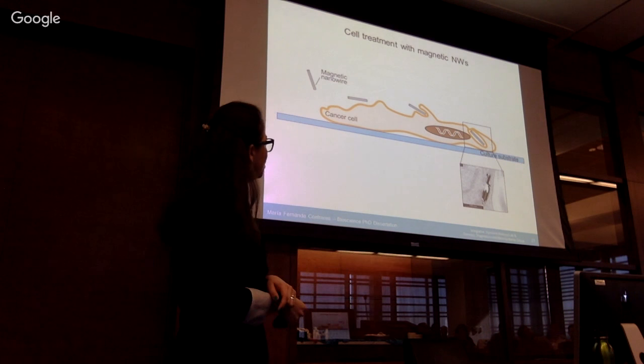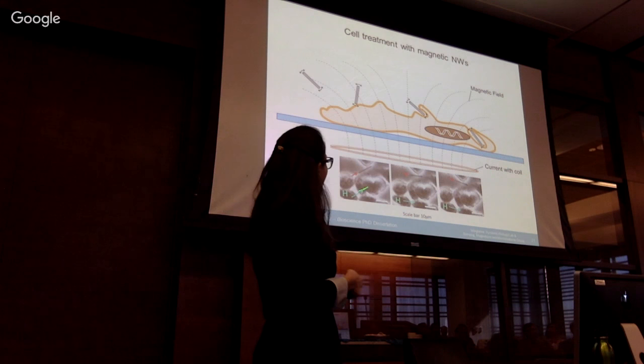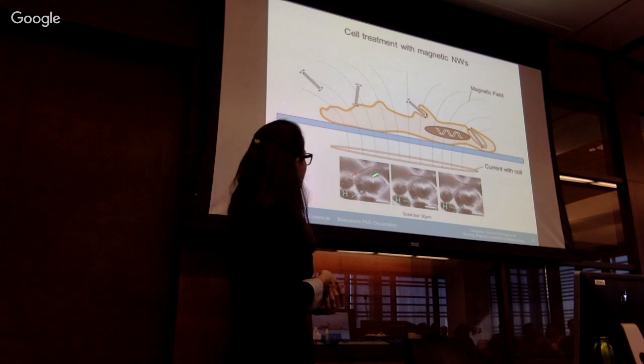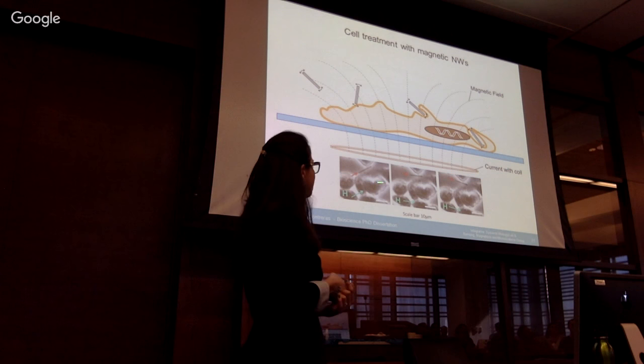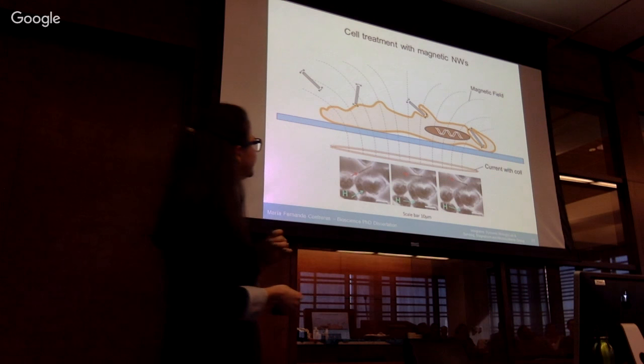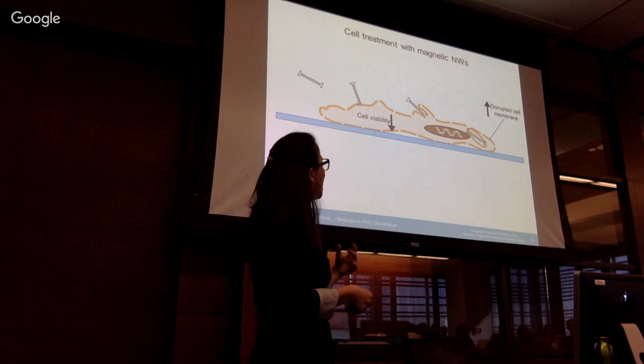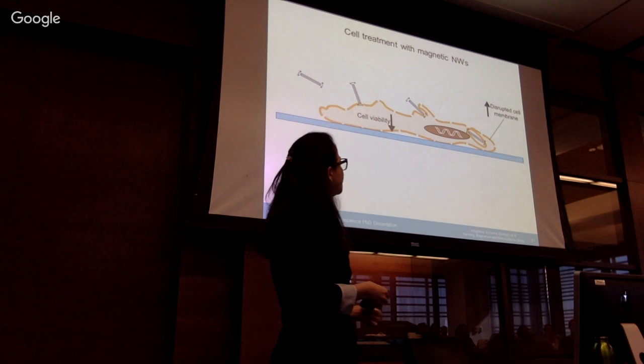Then I apply the field, and the wires would oscillate. I did experimentally corroborate that the wires do move when they are not bound to cells. So this is a nanowire with the red arrow, and you can see how whenever you change the field direction, the wire did align with it, as I described to you at the beginning of the presentation. When you turn off the field, you want to know what happened to the cells, and I rely on these two assays I have been working with, so viability and membrane integrity.